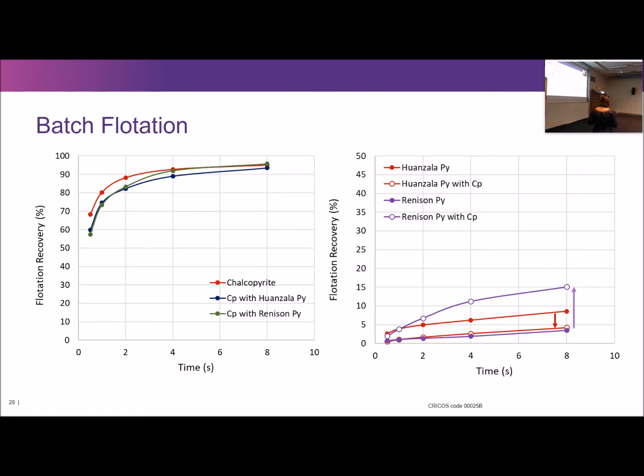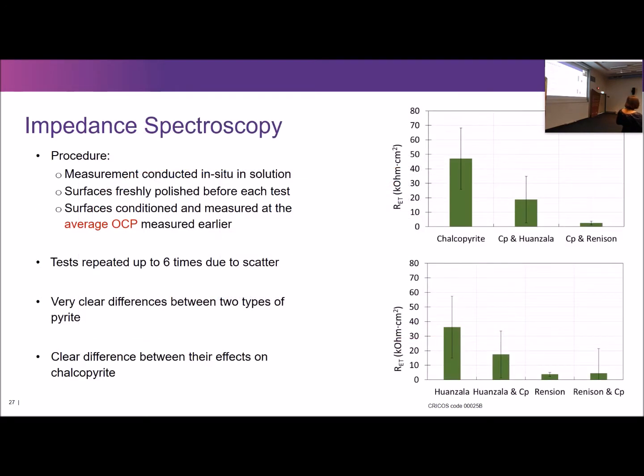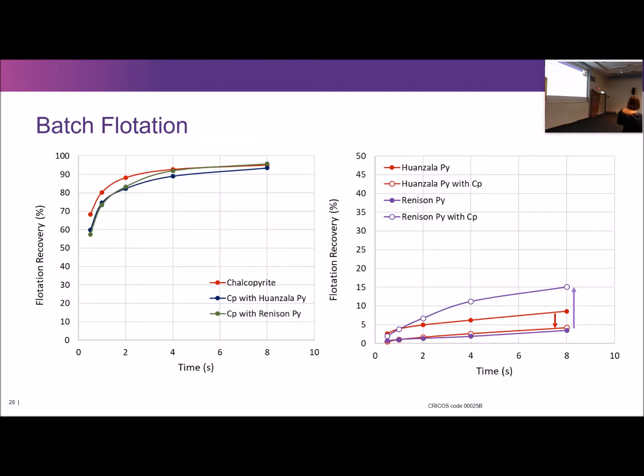Interesting part happens here. When you are floating the pyrite, its natural floatability is very low. So what we expected from previous work is that you mix it with chalcopyrite, it would get better. But it didn't get better, it got worse. Again, slightly, I don't have enough data to fully say with physical confidence that it does definitely go down by how much, but it did, which mirrors what happened here. We expected this to go up, it went down, and guess what? It was reflected in the flotation process.